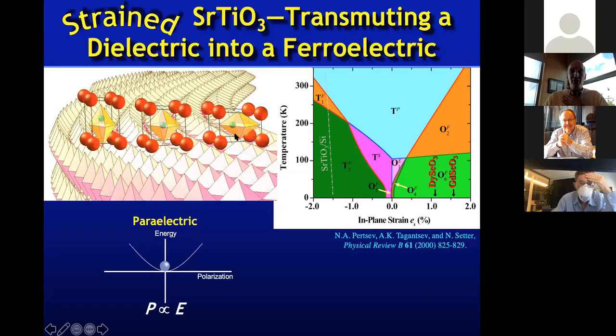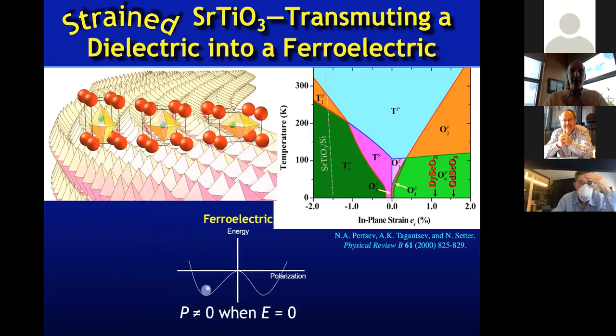But if we change the strain state by putting it in, say, biaxial tension, now that energetic landscape that the titanium ion sits in is going to be lower if the titanium goes off center. So by going off center to the left, where it gets close to those oxygens on the left side, it lowers its energy, or it can do by symmetry the same thing by going off center to the right. So in plane, you can see that there's now a much different energetic landscape. We've gone from having the lowest energy configuration with the titanium in the middle in a centrosymmetric crystal structure to one that has now broken inversion symmetry.